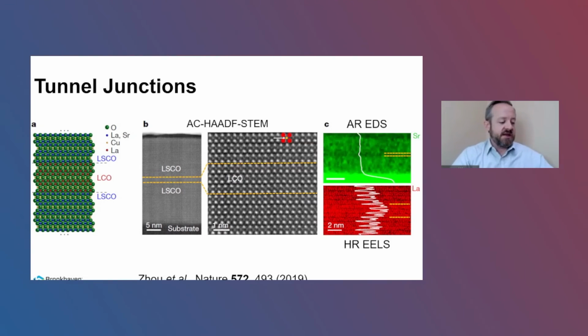What I'm showing here are some films that were grown for this study. This was done with Doug Natelson's group at Rice University. The nominal structure is shown there on the left, which includes layers of LSCO separated by just a few monolayers of LCO. The center picture shows cross-sectional images. This was done by Yimei Zhu's group. I believe MG Han was the one that took these pictures for us using an aberration-corrected high-angle annular dark field STEM. And then on the right, we're showing the strontium and lanthanum signals using atomic resolution EDS and high resolution EELS. And so we see nice interfaces between the different materials here.